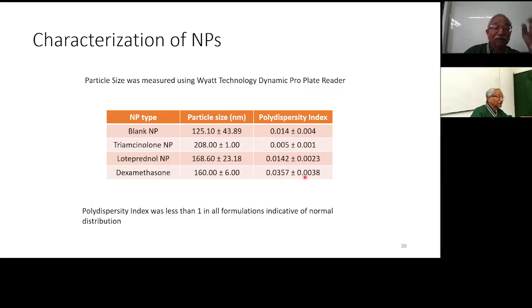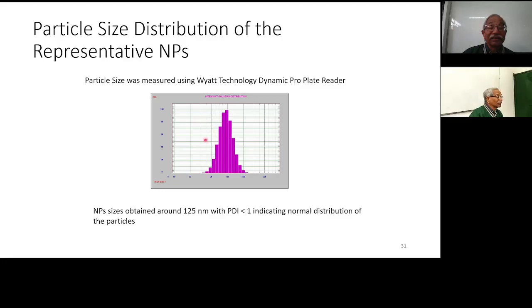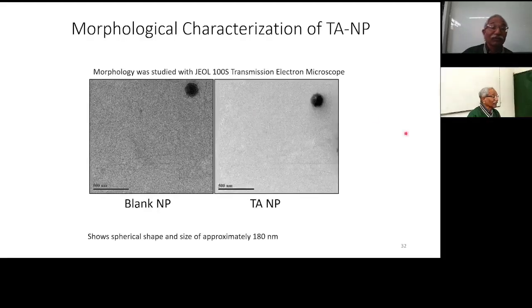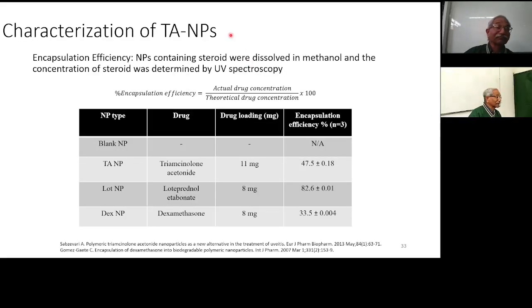And this is how our particle size distribution was excellent there. So we did study the particle size distribution curve. And this is how we got it into our Wyatt Technology DynamicPro Plate Reader. And that was normal distribution, less than 1%. We looked at the particles, individual particles, and this is how blank nanoparticles and TA nanoparticles look under the scanning electron microscopy, with 180 nanometer particle size.